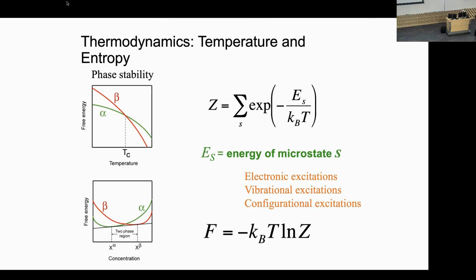So when you pull the lithium ions out, you leave vacancies behind. There's all this disorder that's created. And each kind of decoration of lithium ions and vacancies is a type of configurational excitation that we would sum over. So formally, we've got the energy. For each of these excitations, we need the energy.